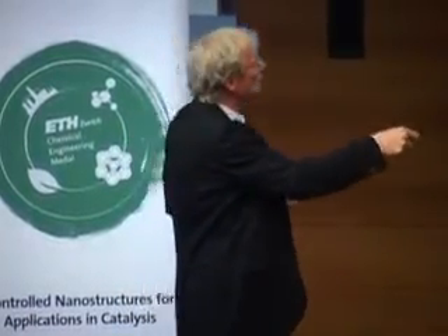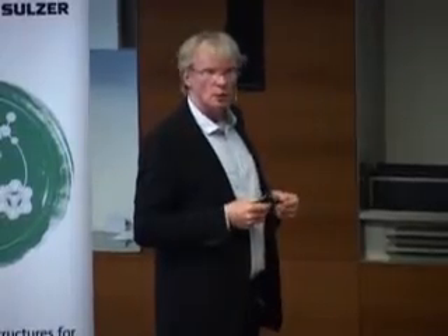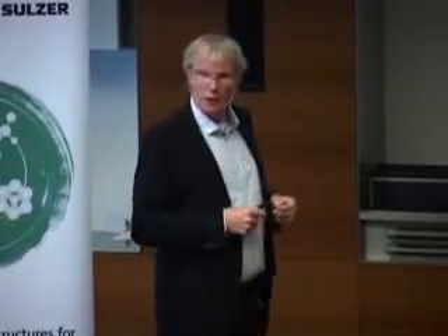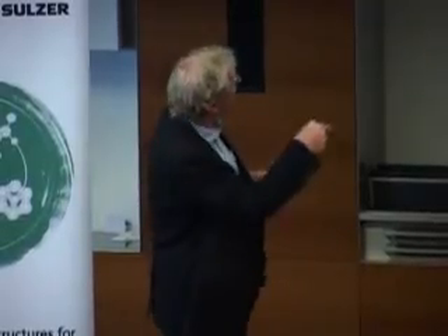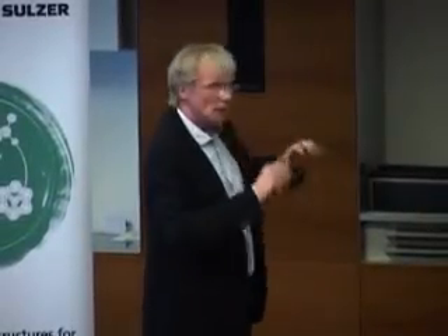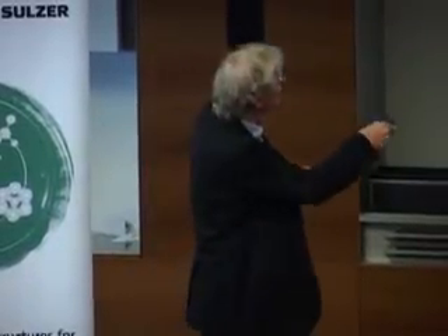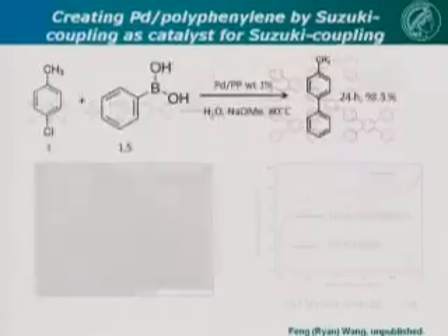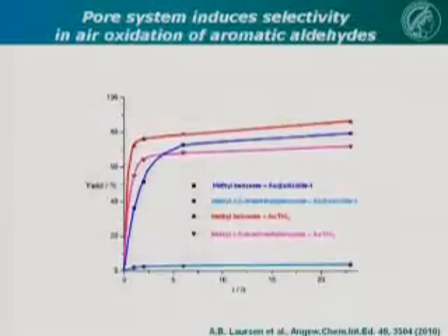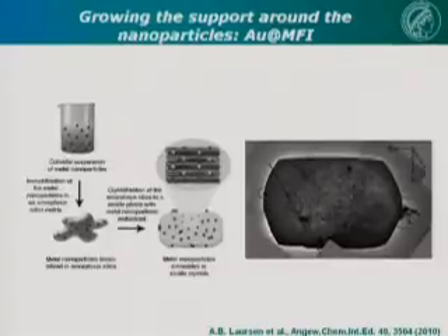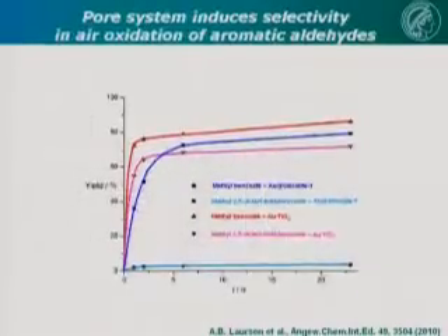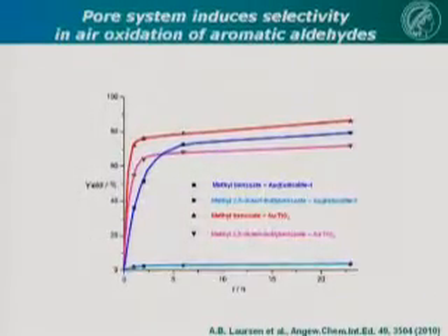This is the matrix. And the way we do it is basically to pre-prepare colloidal particles, and Alfons Baiker is one of the pioneers to use these preformed colloidal particles and occlude them into silica and then expose it to the synthesis conditions for a zeolite. And then you convert the silica to the zeolite, and then the particles are only accessible through the zeolite pores. And that creates selectivity for catalysis.